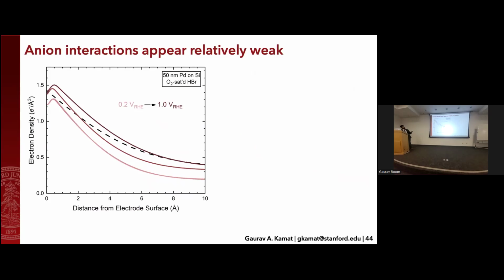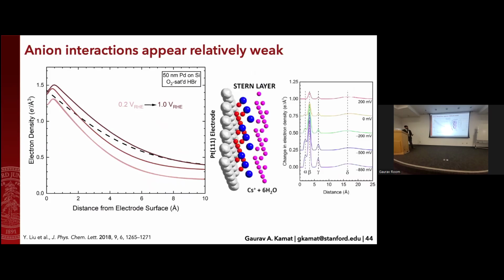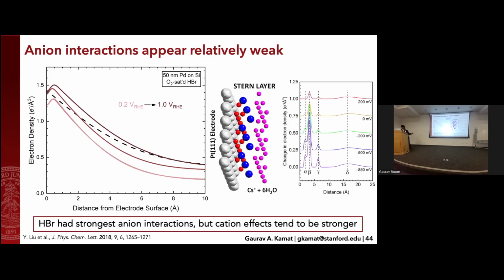Now, I'll mention that these are relatively weak compared to cation interactions. This is a literature example of a platinum electrode where they had cesium present, and you actually get these very strong peaks only a few angstroms away from your surface. And that is corresponding to layers of charge that are forming on top of your surface. Now, it doesn't seem like anions are doing anything nearly that strong. And part of that is because while you're doing a cathodic reaction, you may have an excess of negative charge that can push anions away. However, it's still interesting to note that we can resolve some of these differences. And based on all the previous work, they actually have a lot of implications on catalysis. So HBr has very strong interactions, but cation interactions tend to be stronger.